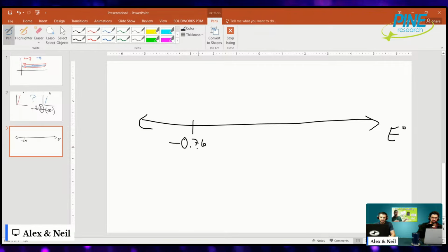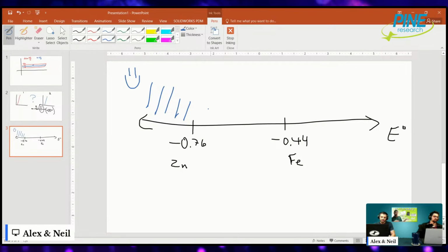Minus 0.76, that's zinc oxidation, and then minus 0.44, which is more positive than that, is iron. So what this means is that in this zone here, we're happy. Nothing is oxidizing. In this region, negative, roughly speaking, right here, that's negative of the zinc and of the iron, right? So negative prefers the reduction reaction. That's not corrosion. Corrosion is the oxidation side.